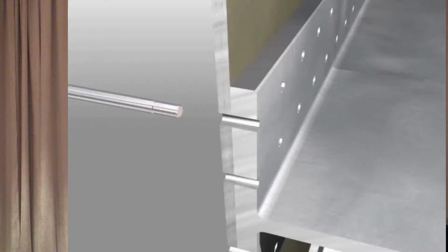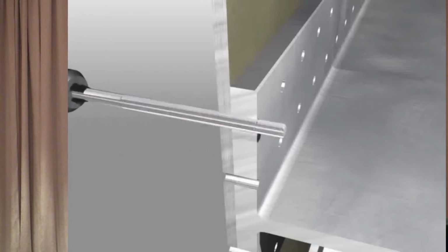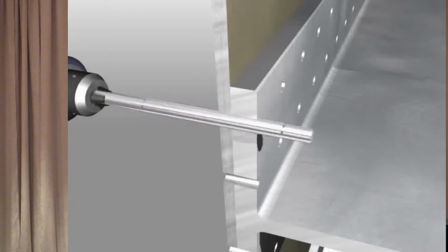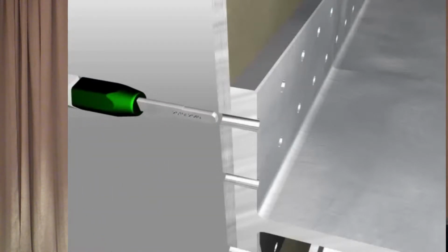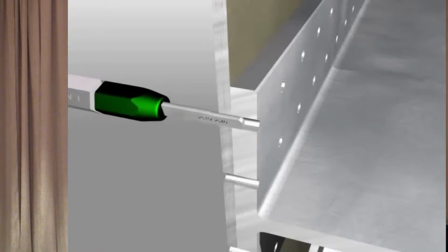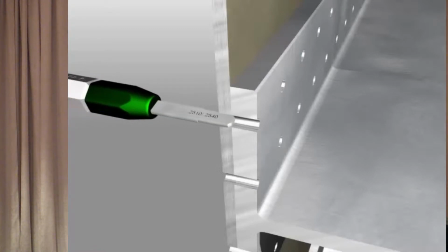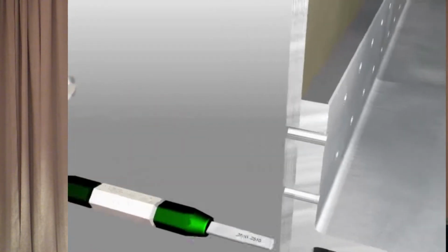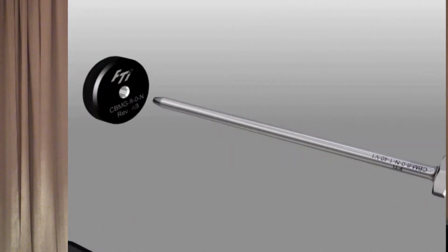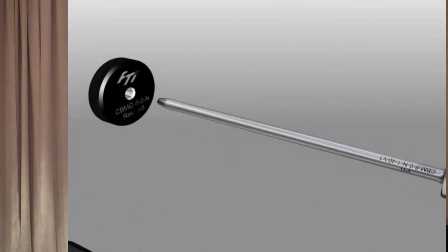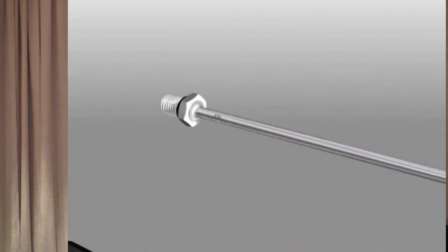So you've got that ream step to get that hole. I've had a lot of questions in the last day about perpendicularity. As long as you're able to get within 2 degrees vertical to the hole, you'll be fine. Quality is important, so we do ask that that hole be checked prior to the treatment. And then for fastener holes in aircraft, a split sleeve is loaded onto the mandrel after the mandrel is checked for wear, loaded onto a hydraulic puller.